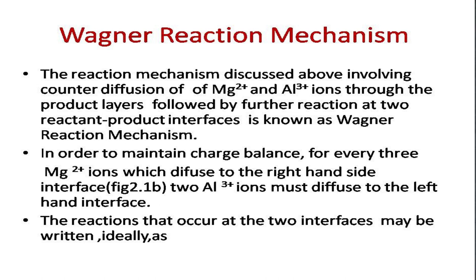Wagner is the scientist who has given all these mechanisms for the formation of such spinels. The second case is, in order to maintain a charge balance. Now I am going to explain why there was a difference in the layers, one side small and the other side bigger. For this purpose, you have to look at the second sentence. In order to maintain the charge balance, for every three magnesium ions which diffuse to the right hand side interface, two aluminum ions must diffuse to the left hand side.